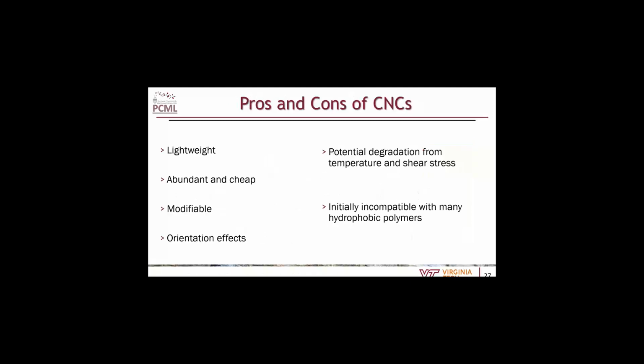So what this means is we have to look at cellulose nanocrystals and their possibility to be used in industrial processes. They're great because they're lightweight, they're abundant, they're cheap. You can modify them with some decent chemistry, and they also shear thin, which can make processing them potentially a little easier or a little more difficult depending on what you're working with. However, they clearly see potential degradation from shear stress, and because they're wood, they're also not going to like really high temperatures either. And then they're not nearly as cheap and easy if you want them to be compatible with hydrophobic polymers, because then you have to spend all the time and money changing their surface characterization.